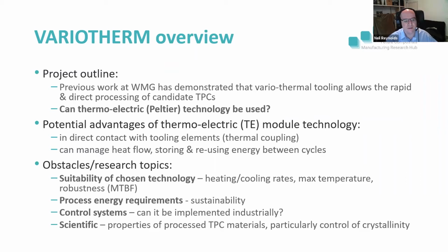The reason we're interested in Vario-thermal tooling is it allows us to very rapidly vary the surface temperature of a tool, so we can basically melt process thermoplastic polymers isothermally prior to then cooling them in a controlled way. The advantage of that is we can get to very short cycle times while still maintaining an isothermal process window.